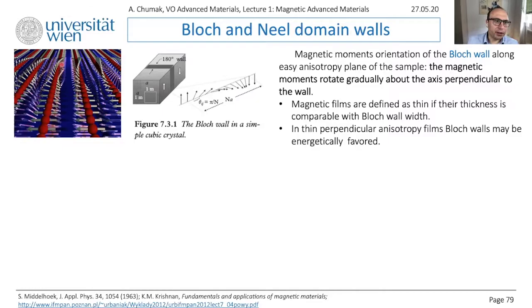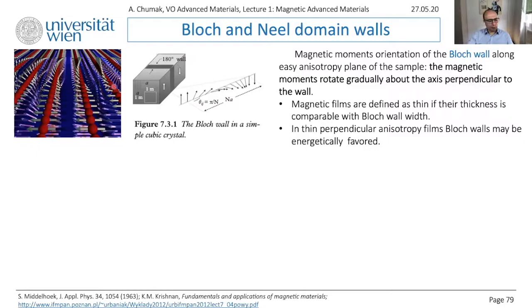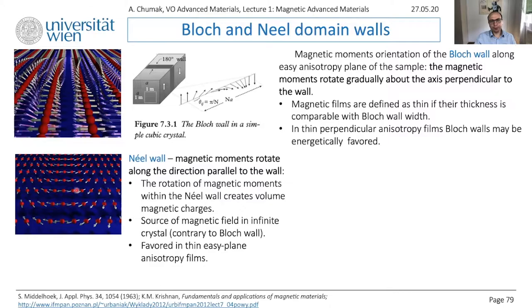This is the Bloch domain wall, as shown in this colorful picture. The Néel domain wall is typical for thin films, where form anisotropy wants to keep spins in-plane. It is unhappy when a spin is staying perpendicular to the film — this costs a lot of energy. Therefore there is another way: the magnetic moment is always in-plane and rotates from one to the anti-parallel state by turning within the plane. This is named the Néel domain wall. Of course, they are realized differently depending on film thickness. Here there are two graphs — wall energy and wall width as a function of film thickness.